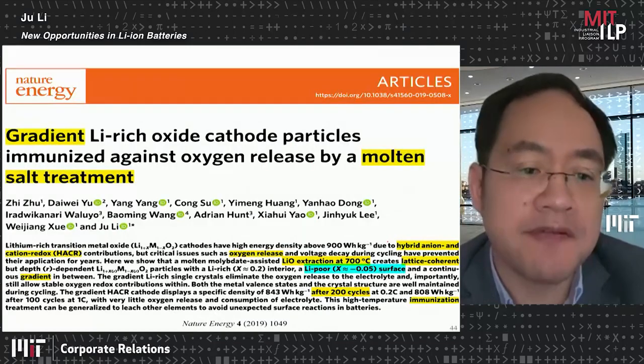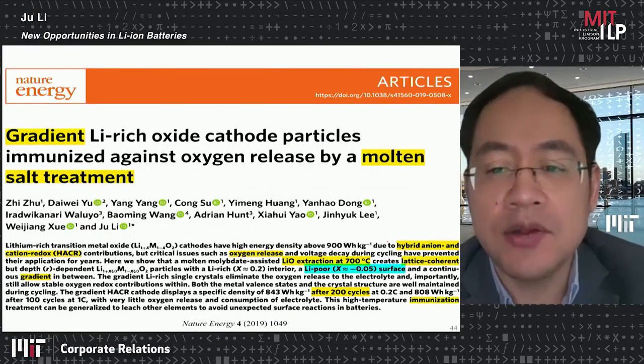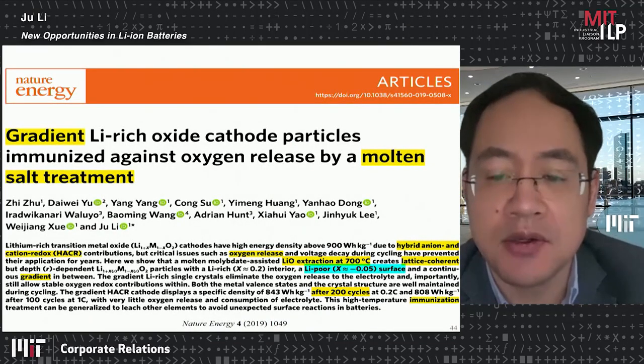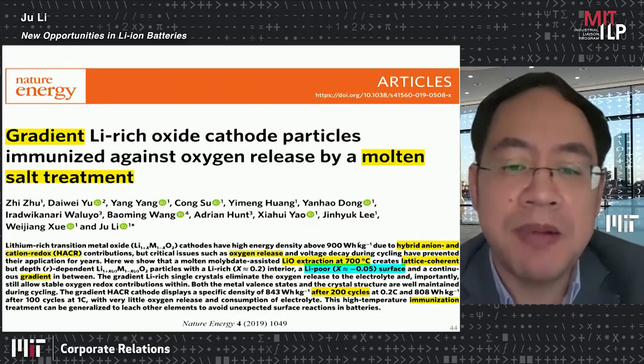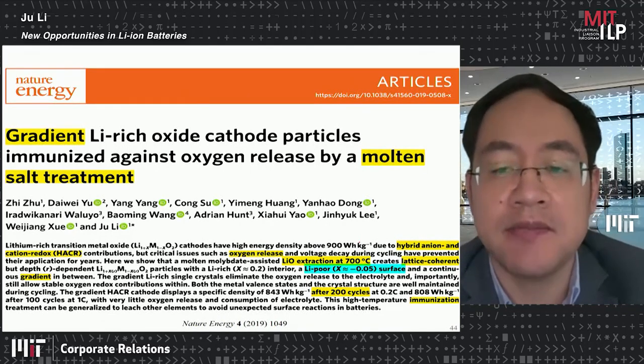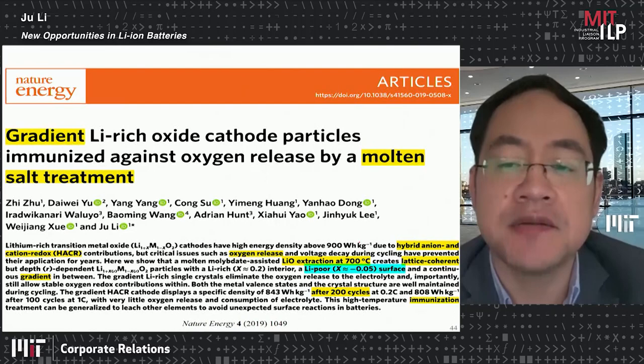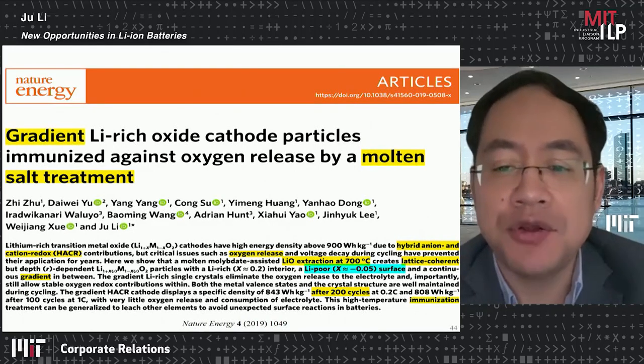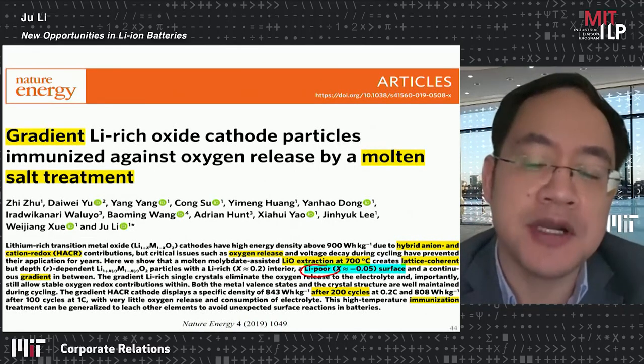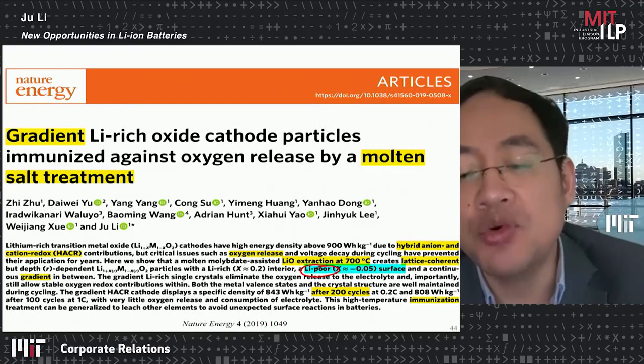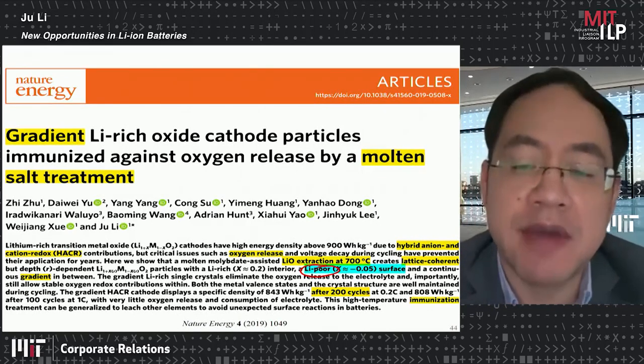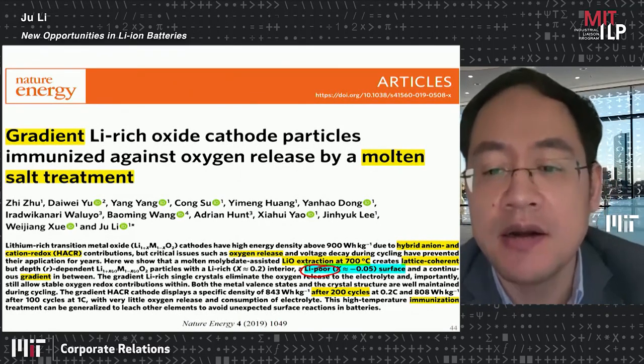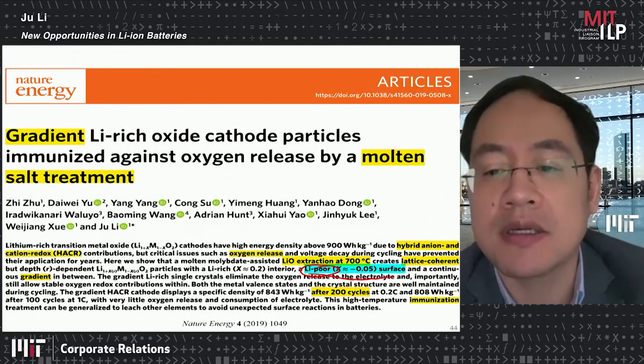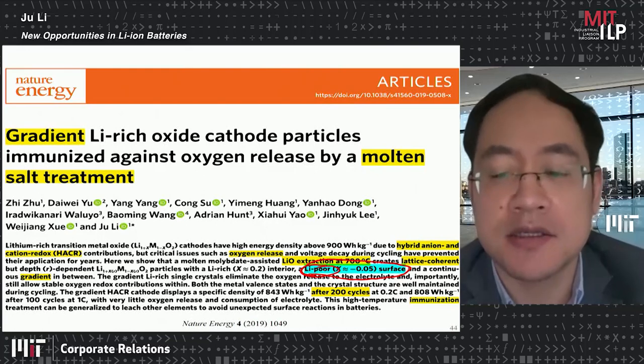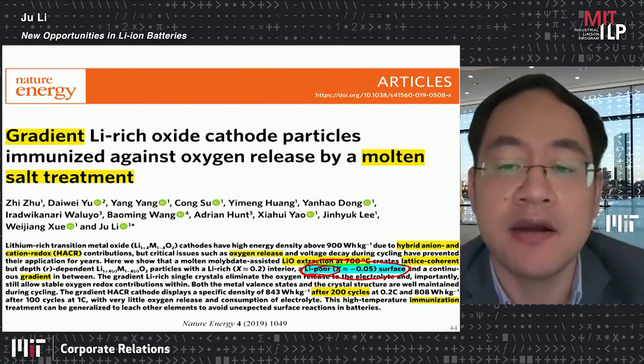So what we have done is trying to reverse the trend. Knowing that replacing transition metal by lithium elevates the oxygen energy level, if we do the reverse, if we have more transition metal elements in the lithium layer, actually create this lithium-poor surface, then we can protect the surface oxygen. So that's the main idea.